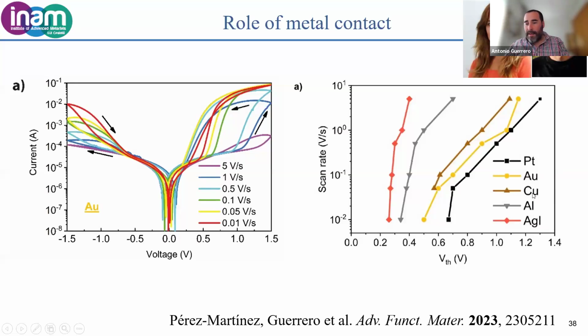But with other metals like aluminum and copper, these materials react faster, and then we don't need to apply such a high voltage to get the electrochemical oxidation. And in the case of silver iodide, the silver is already oxidized, it's not silver 0. This is the case where we have the lowest applied voltage to get the set voltage. So silver iodide can be used as a material for low energy applications.